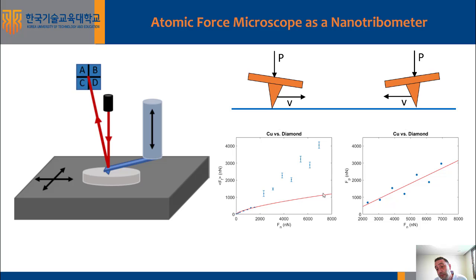So once we have determined the shearing and fitted the low force regime with the equation I showed you previously, which is the product of the shear strength times the contact area, we can simply subtract the shearing fitting curve from our experimental values to calculate the ploughing force as a function of the normal force. And this then allows us again to fit the ploughing force with a linear curve, and the slope of this curve is then the ploughing coefficient.